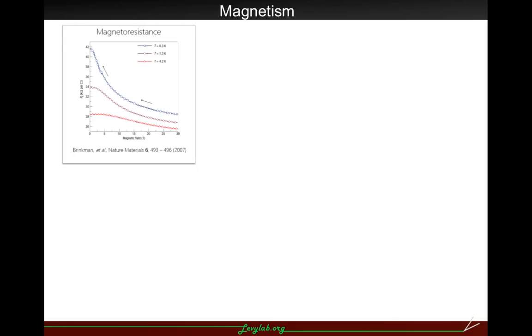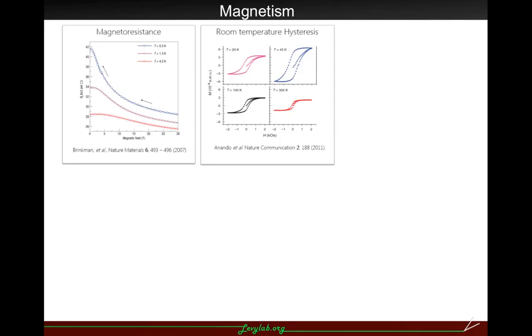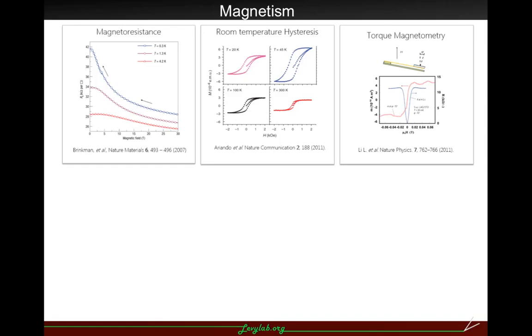Magnetism was first reported in 2007. This came as a big surprise, considering the bulk state of neither LAO nor STO shows any sign of magnetism. A large negative magnetoresistance has been observed, on the order of 30%. In 2011, Arenholz studied the zero-field-cooled and field-cooled magnetization as a function of temperature. The magnetization loop has been detected under different temperatures. Notably, a ferromagnetic response is observed in the form of a hysteresis loop extending up to room temperature.